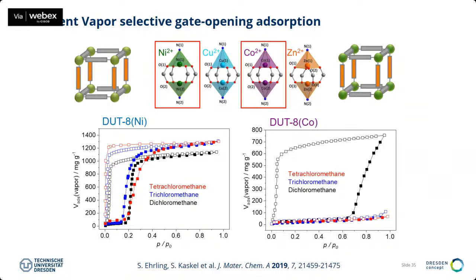And then you can also introduce selectivity. If you have a MOF which is not so easy to open, like the cobalt MOF compared to the nickel DUT-8, the nickel DUT-8 would open for dichloromethane, trichloromethane, and tetrachloromethane. But the cobalt MOF, because it's more difficult to open, only opens for the dichloromethane, but trichloromethane and tetrachloromethane are not able to open the MOF. So this allows you also to introduce selectivity with the responsivity of the metal organic framework.